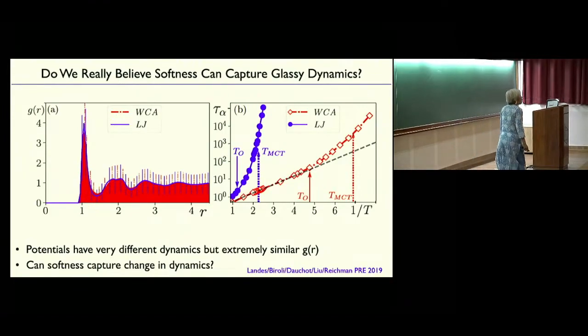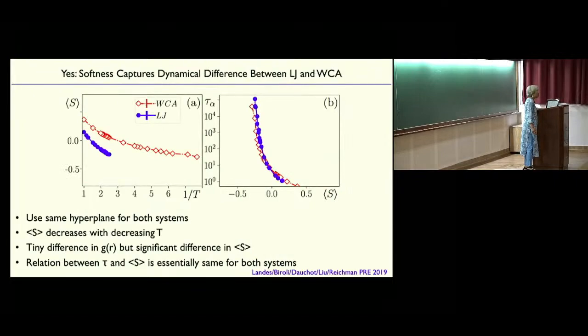We scale this x-axis by an appropriate temperature, energy scale. I know that there are some changes in fragility. You cannot get them to collapse. Actually, they're quite different. There's a nice paper by Gilles Tarjus and Ludovic Berthier showing that these two are really quite fundamentally different, and arguing that the attraction can't just be a perturbation in this case. It really makes a huge difference.